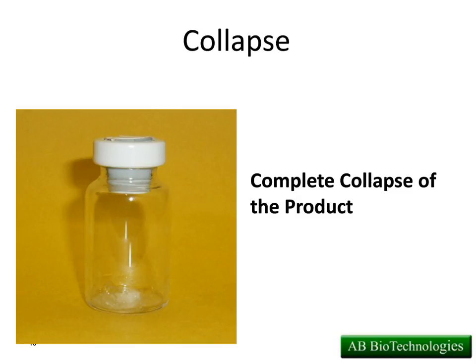You can imagine the reconstitution is going to be terrible, because one of the benefits we get when we freeze-dry and get a very nice cake is that that cake is very porous, because where all the ice crystals used to be, now they're hollow, empty spaces. So when we rehydrate and add our reconstitution fluid, it runs into those spaces and really quickly hydrates. So we've essentially closed those down. There are no open pores in a collapsed product.